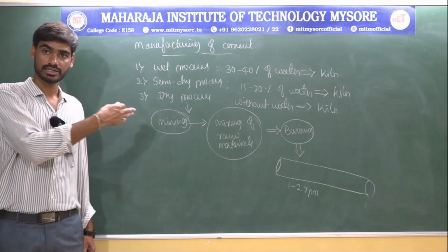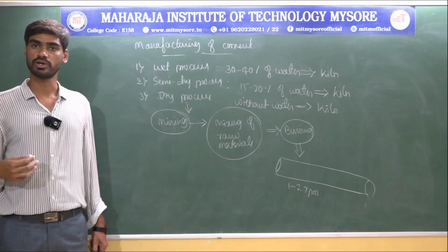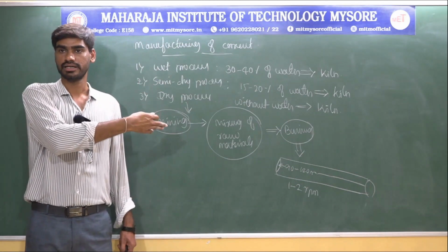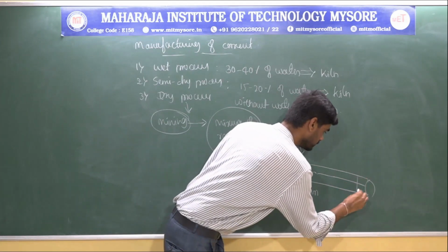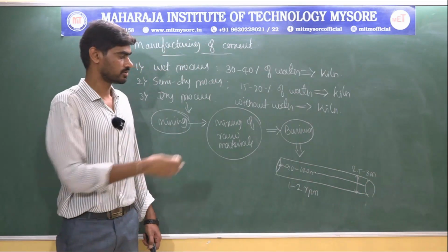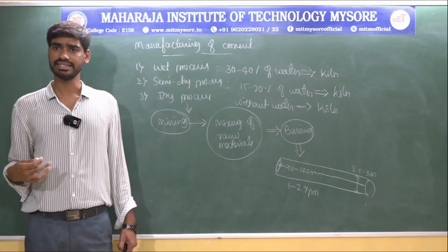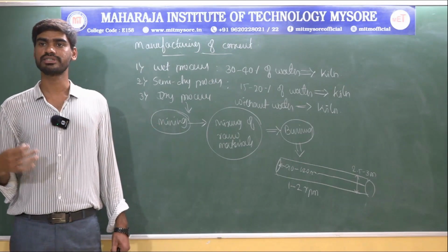The steel tube is about 90 to 120 meters long, and the diameter of the rotating kiln is about 2.5 to 3 meters. The kiln rests on roller bearings in a slightly angled position, supported by masonry or concrete columns.